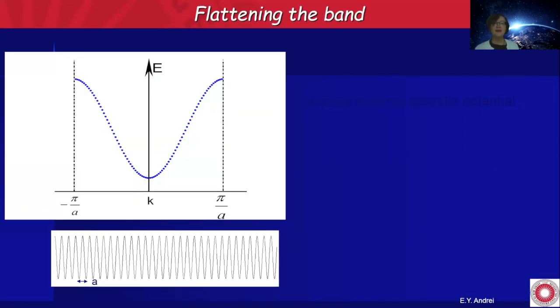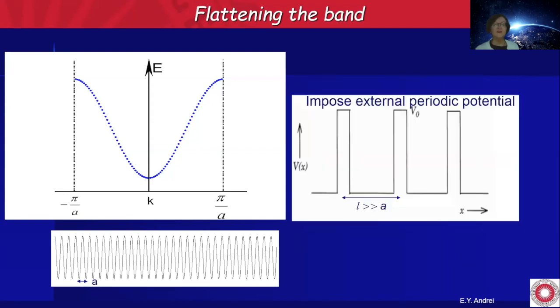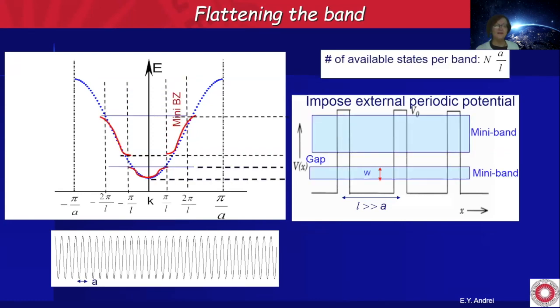So how can we make a flat band? Let's start from a regular parabolic band here in a crystal. Here we have the lattice spacing. And one way to flatten the band, and that's a very simple way, is to put your crystal in a periodic potential whose period is much larger than the atomic spacing. And what happens then, you break up the Brillouin zone into pieces.